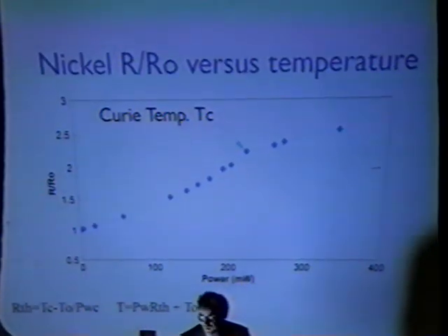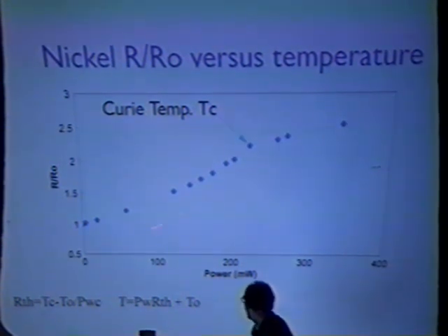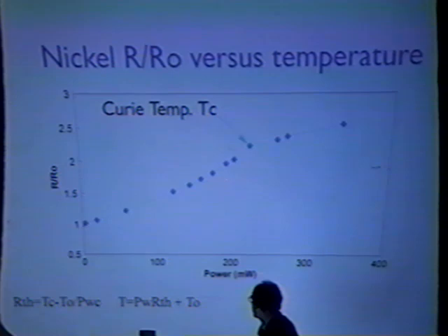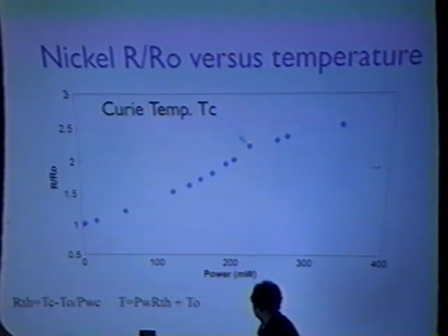by all the instrumentation. And first of all, it is important to know the temperature of the sample. So, monitoring the behavior of the electrical resistance of the nickel film, you can clearly see the cross through the Curie temperature, where we have the loss of the ferromagnetic properties of the nickel.